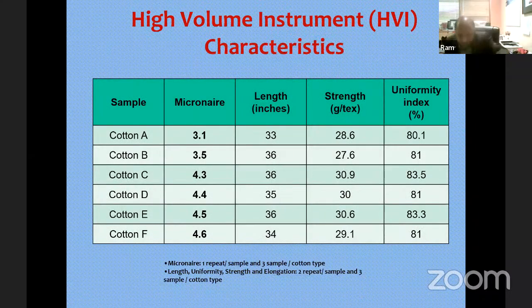So I have taken different types of cotton. The lower the number, the more immature it is. So 3.1 is an immature cotton. That is discounted cotton. And 4.4, 4.5, 4.6 are those regular cottons which are loved very much by the textile industry. 3.4 and above are good cotton, particularly in the range of 4.3 to 4.4. I need to show you that 3.1 absorbs more crude oil compared to 4.6, whereas 4.4, 4.5, 4.6 are perfectly mature cotton, which the textile industry uses. The textile industry is not favorable to any cotton less than 3.4.